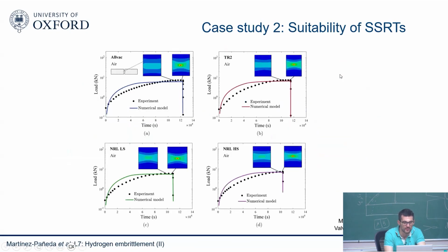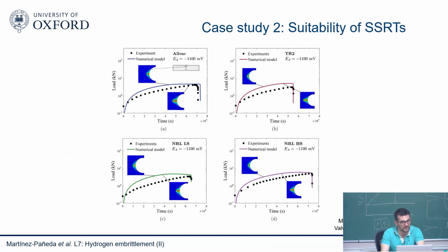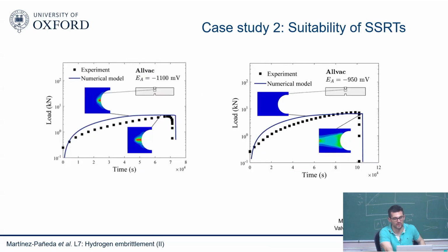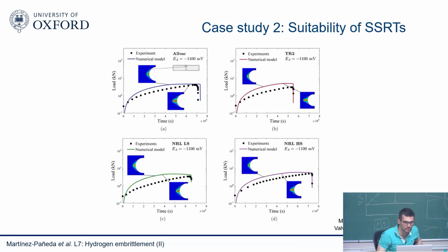So the model not only could capture the ductile phase, and then we put hydrogen in and it captures the hydrogen case very well, but we changed the hydrogen environment, and the model also captures well the time to failure, more or less. It's not perfect, but it's close enough, I would say. So this is good because it means that we trust the model. The model seems to be able to capture all the data that we have.